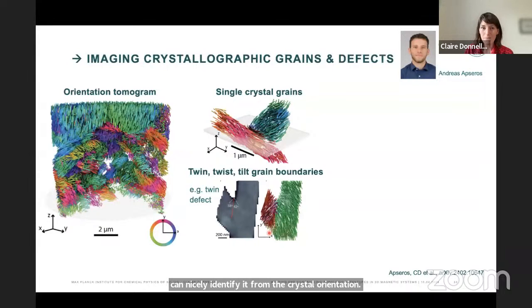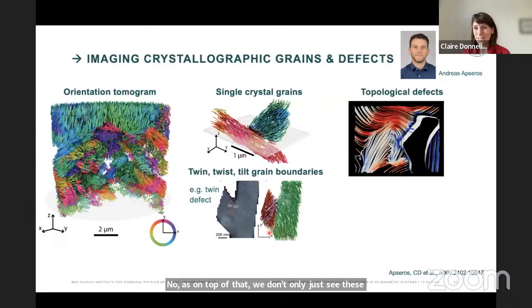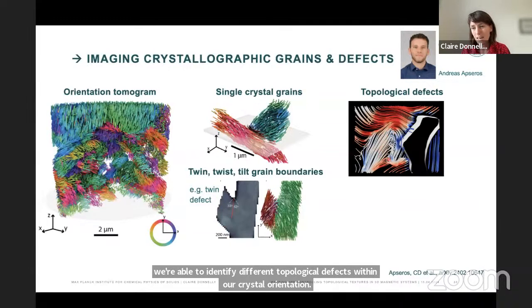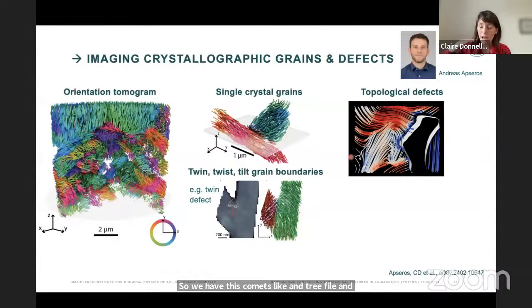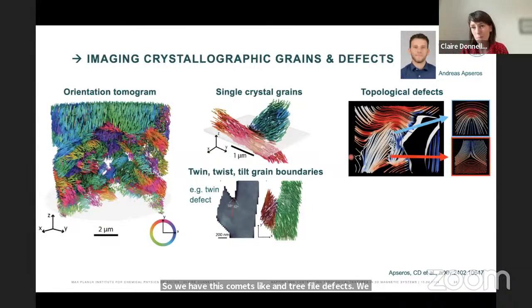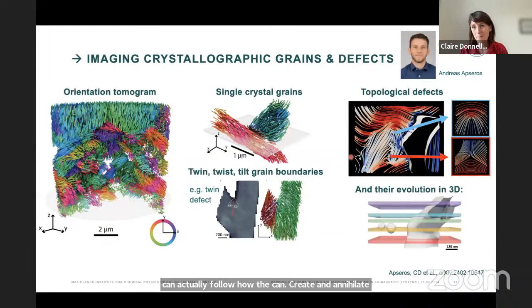On top of that, we don't only just see these grain boundaries, but we're interested in topology. So we were also looking at the different types of defects that we can see within our system. And indeed, within our more merged, denser areas, we're able to identify different topological defects within our crystal orientation. So we have these comet-like and trefoil defects, and we can actually follow how they create and annihilate, so they merge, if we follow them through three-dimensional space. This was very exciting to see now that we have this new capability.